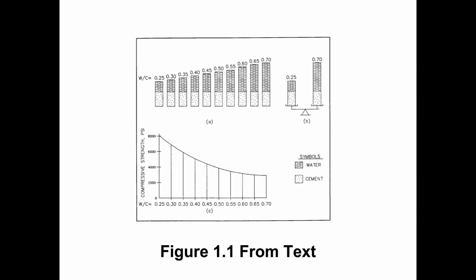So if you've got two samples of material and they weigh the same, but one sample is larger than the other, then what that tells you is that the larger sample is less dense. If it's less dense, that means that there's more space between the particles within the sample. And so that's exactly what happens with our concrete. As water cement ratio goes up, we have more space between the hydrated cement grains within our cured concrete. And so that means we have more of a lattice type structure than a dense type structure, a solid type structure. And so what figure C is showing us there is that the denser structure with the lower water cement ratio is going to have a higher compressive strength.